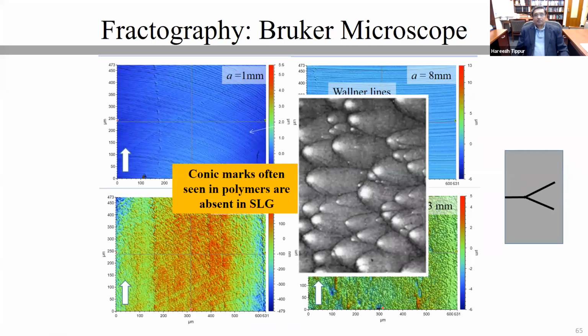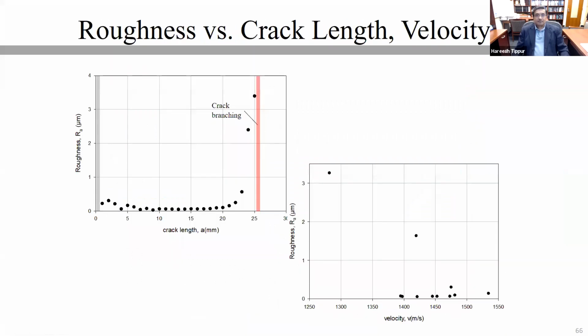One thing that I want to point out before I go to the roughness itself is the conic marks that are often reported to be part of the fracture surfaces in polymer literature are completely absent in all of our measurements. So I think this is simply an artifact of what we normally see in polymers, which could be the inhomogeneities, or it could be the viscous effects that are dominant in polymers. So we don't see any of that in soda-lime glass.